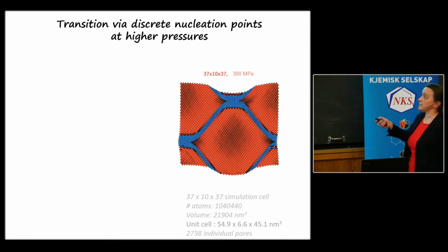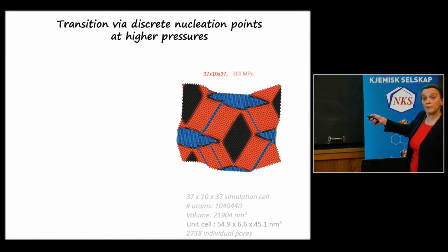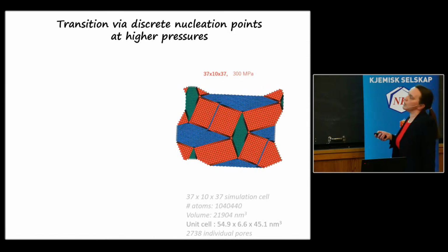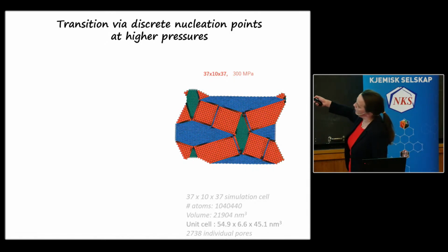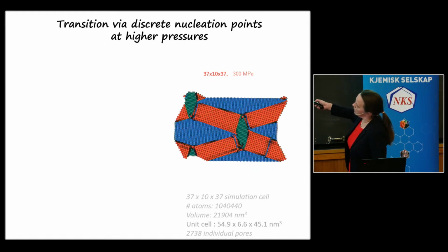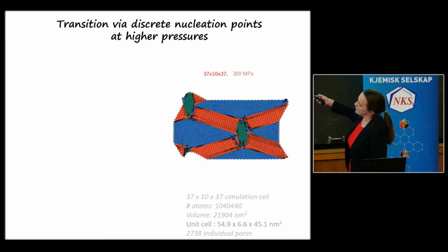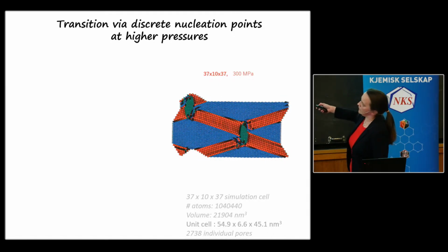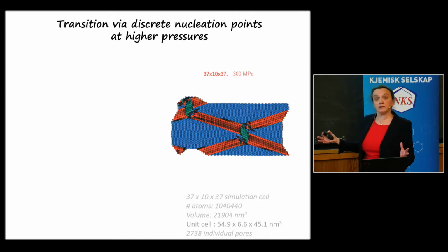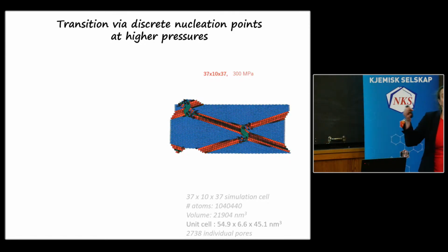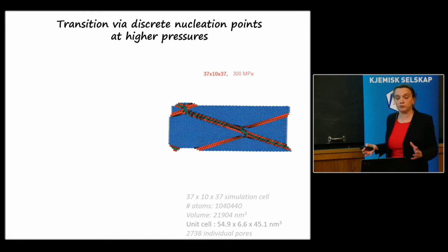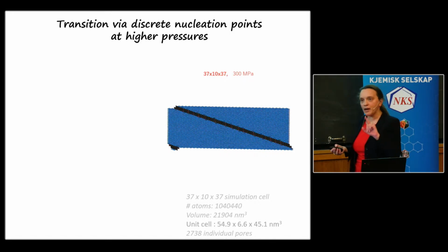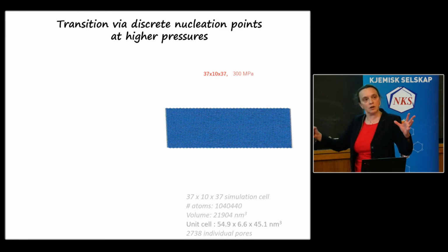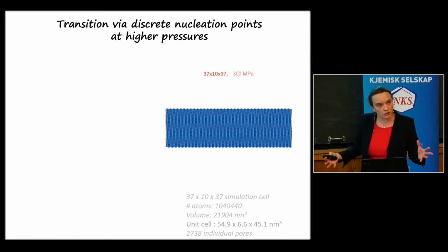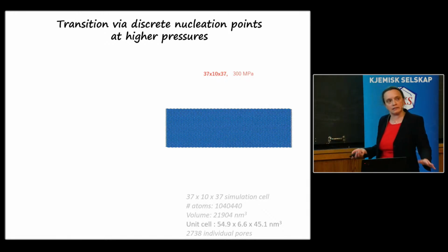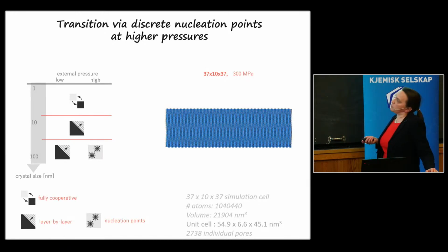Here you can see that things happen at nucleation points. We can have strong deformations. You can also see formation of domains here. And so you clearly see that depending on the size of your crystal, you can see other dynamics. For that reason, the terminology spatio-temporal evolution has been introduced in the field, where the dynamics is affected by the spatial extent, or the spatial dimension. Length and time scales are correlated. So this is what we did here.